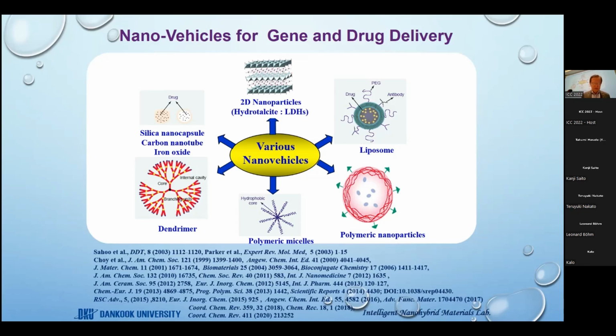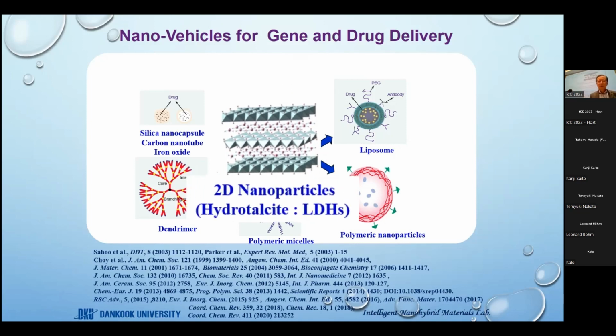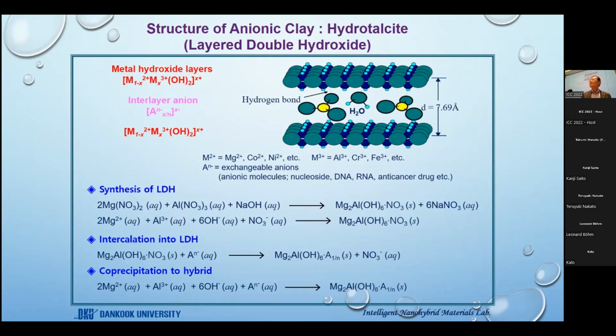But I'm very much interested in the 2D nanomaterials, as I mentioned earlier, particularly the anionic clay, such as hydrotalcite. Well, probably many of the colleagues here understand the crystal structure of layered double hydroxide, but it is very important to understand the crystal structure of brucite, magnesium hydroxide. In the brucite structure, magnesium ions are octahedrally coordinated with hydroxyl ligands to form an octahedron. And these octahedrons are bound to one another by sharing the edges to form an infinite sheet. And this infinite sheet is stacked on top of each other to form a multilayer.